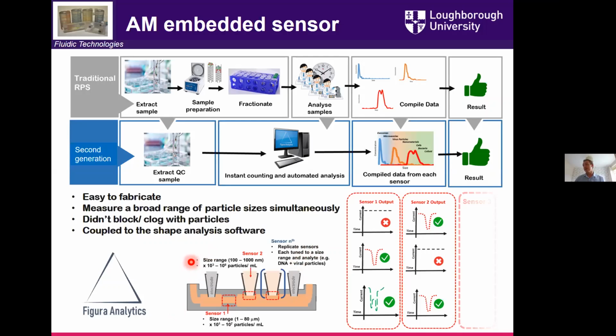We've got a flow reactor where you can flow your particles or products in. It goes through a series of channels and out the other side. And what I've been showing you is sensor one, a way of characterizing particles using resistive pulse sensing. What we've also now embedded in here are different sensors, and then we can tune those sensors for different properties, whether it be optical or particle sizing, all the way down to tens of nanometers up to tens of microns.